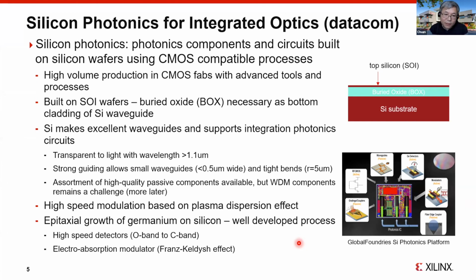Germanium with some addition of silicon in it also provides a way to make electro-absorption modulators based on the Franz-Keldysh effect. So basically, when you apply a voltage, the band gap of germanium will shrink, and you can use that to make an electro-absorption modulator.